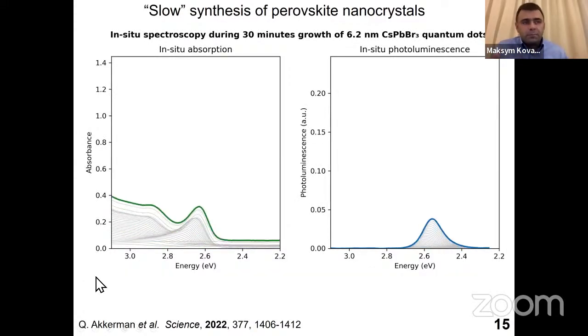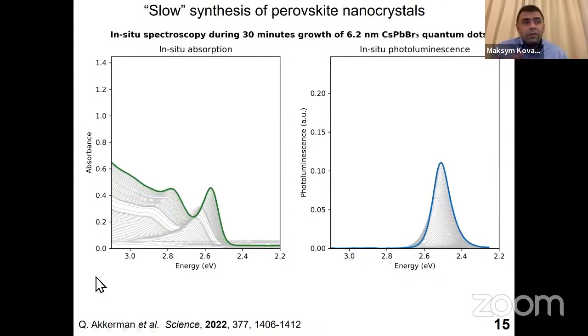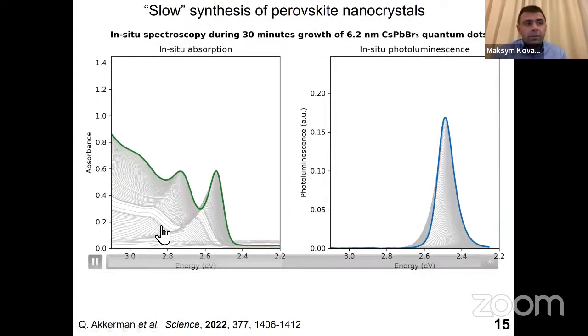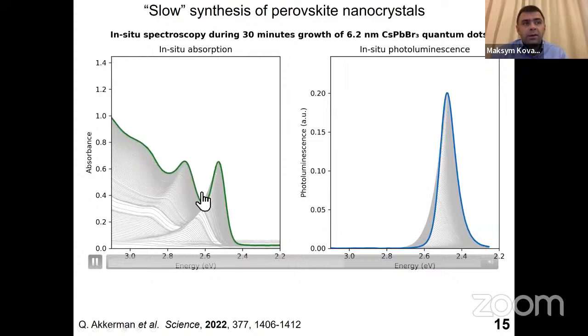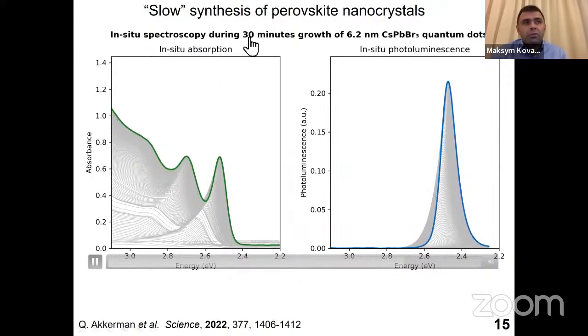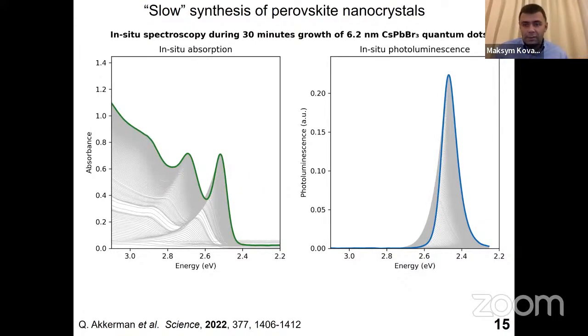Here you see that you can actually have this whole synthesis much slower. So you see the absorption spectra of these quantum dots measured within 30 minutes. So this whole progression is half an hour instead of 1 second or less. So now you have a synthesis which is much slower, much easier to control, and everything occurs at room temperature. So you don't even need to heat it up. So you may ask, what did we change?